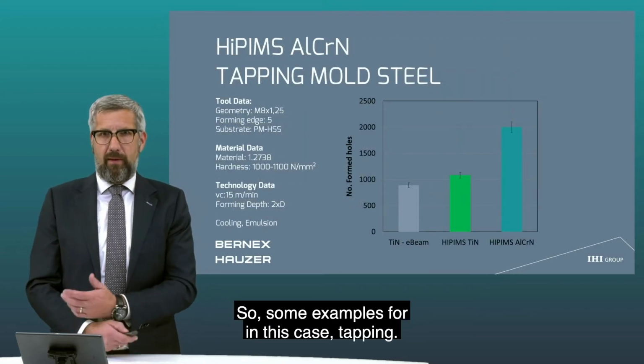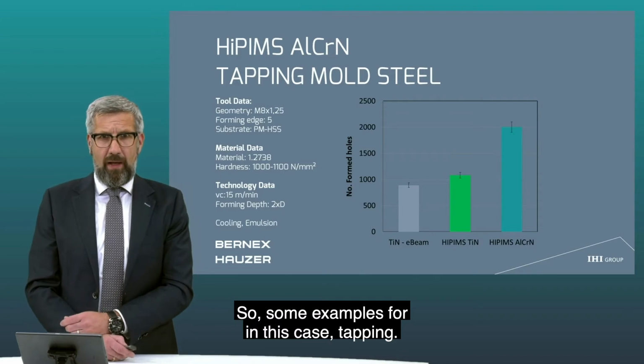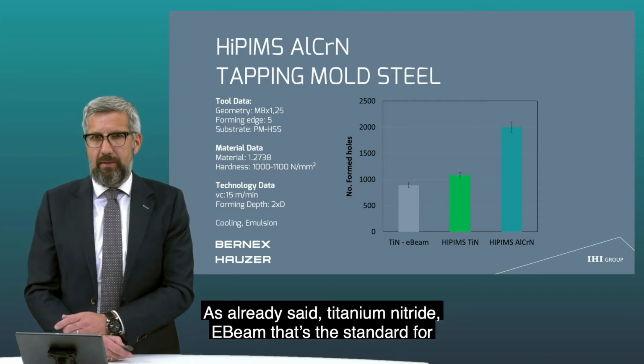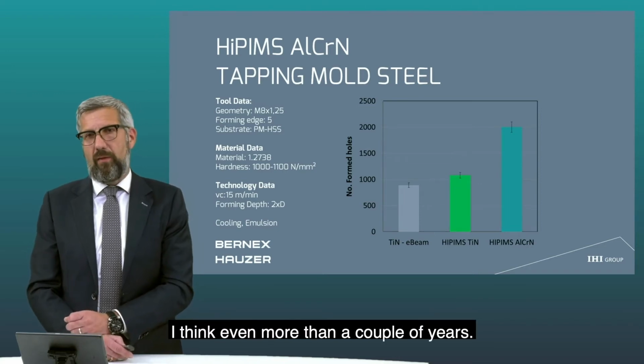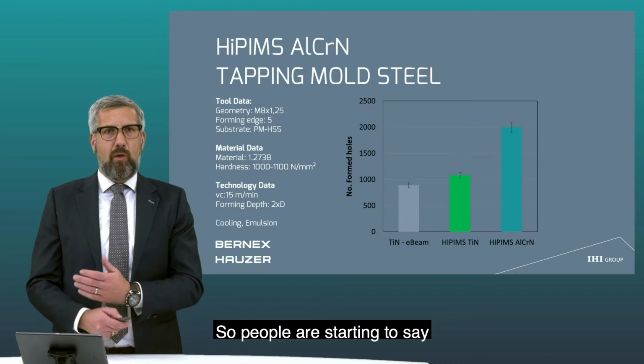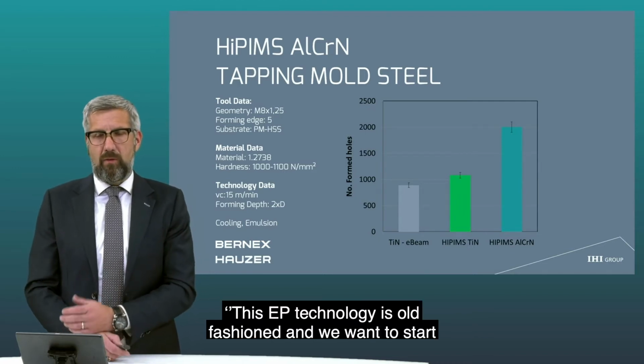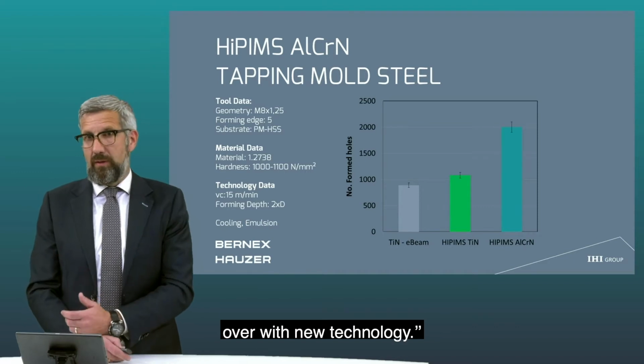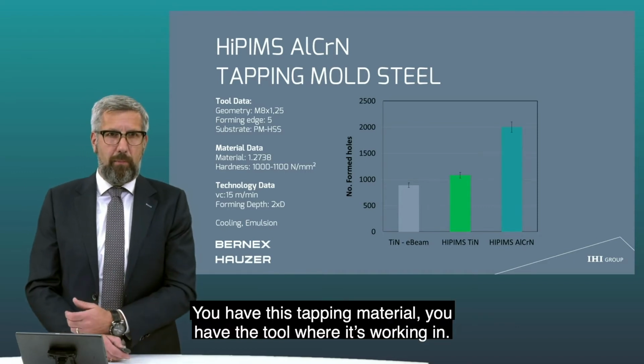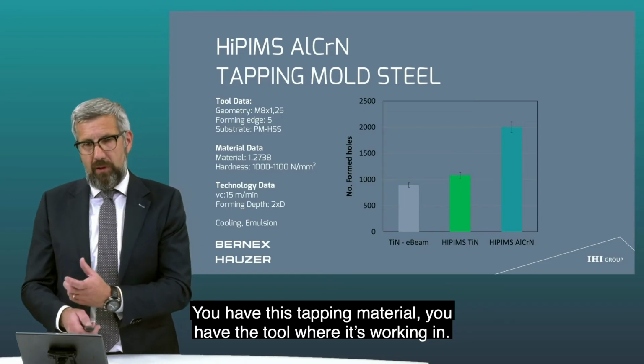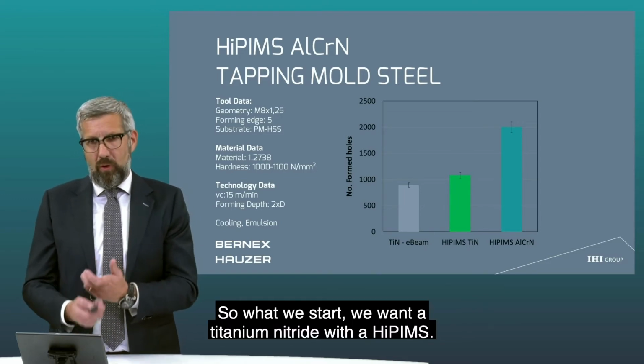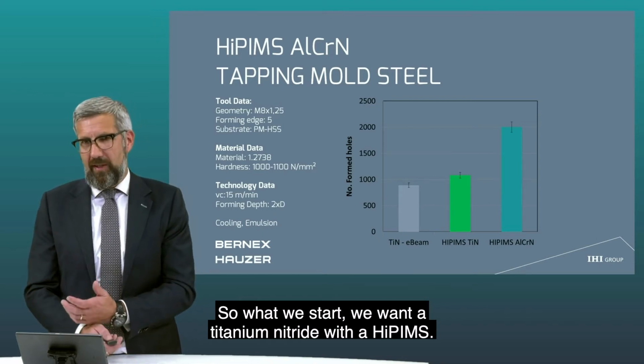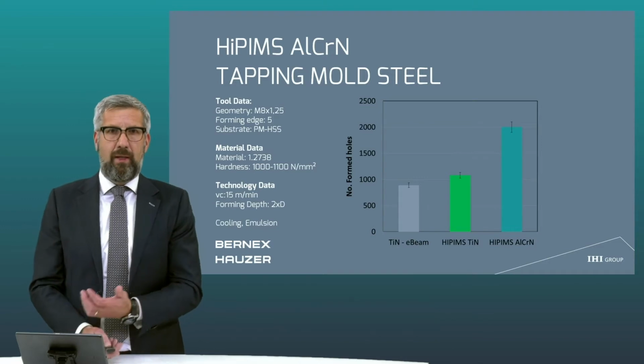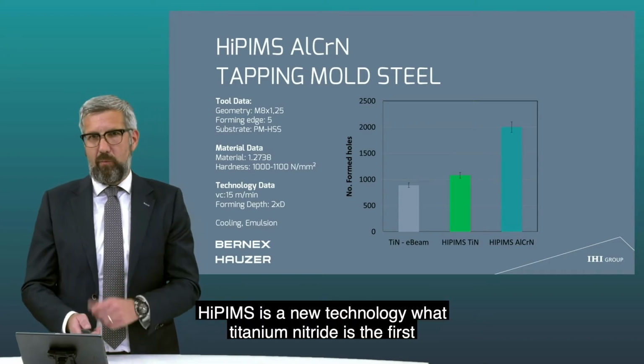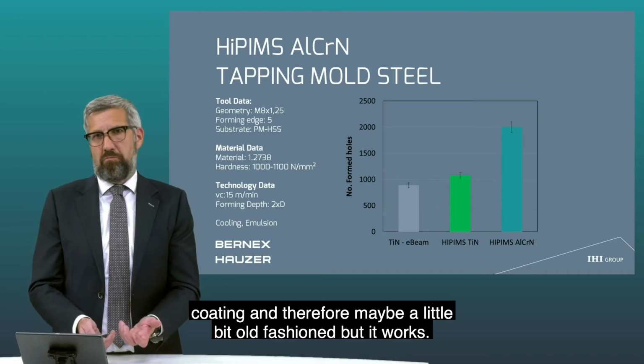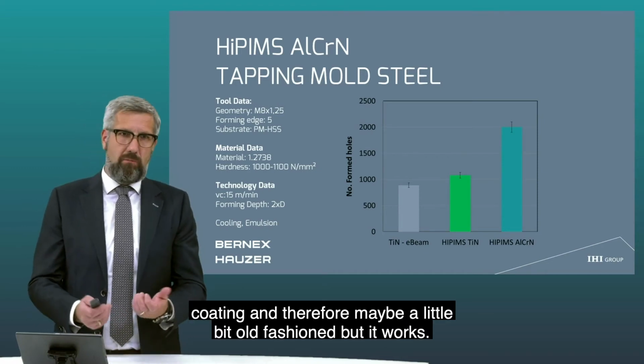So some examples, in this case for a tap. Tapping, okay, as already said, titanium nitride, E-beam, that's the standard for a couple of years already. I think even more than a couple of years. So people are starting to say, hey, this E-beam technology is old-fashioned and we want to start over with new technology. And you have this tapping material, you have the tool and the material it's working in. So what we start with is, okay, we want to do titanium nitride with HiPIMS. Titanium nitride works. HiPIMS is a new technology, but titanium nitride is one of the first coatings and therefore maybe already a little bit old-fashioned, but okay, it works.